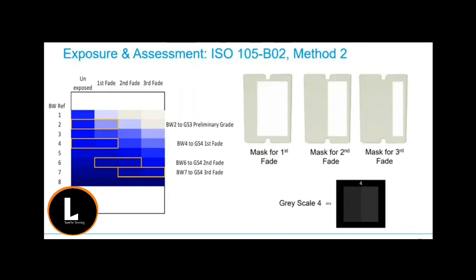On the second fade, changing to the second mask on screen, you are looking for blue wool reference fabric number 6 to complete a shade change to grayscale 4, which would take approximately 160 hours. And then on the third and final fade, changing to the third mask that you can see on the screen, you're looking for the blue wool reference fabric number 7 to complete a shade change to grayscale 4, which would take approximately 320 hours.